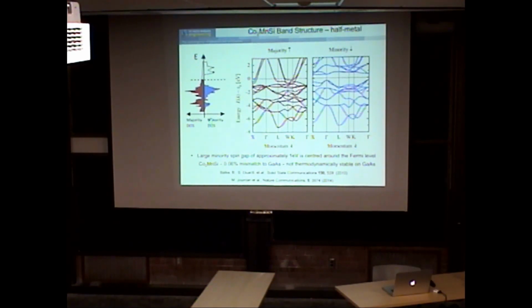We can draw this as density of states, with red for majority and blue for minority. And we see here we have the band gap for minorities. I pointed out here the mismatch to gallium arsenide is 0.06%. So it's a very good lattice match, so we would like to grow this on gallium arsenide.